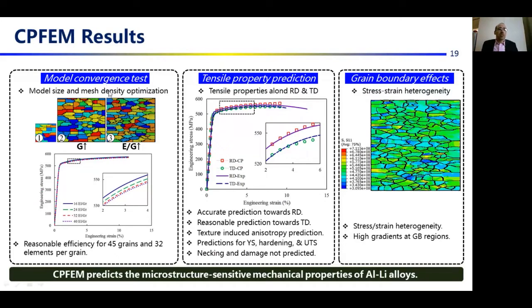For the CPFEM results, firstly, the model mesh convergence ensures the accuracy and efficiency of the CPFEM models by adjusting the grain numbers and elements per grain numbers. Tensile property prediction shows that CPFEM can predict the microstructure-sensitive anisotropic tensile properties consistent with the experiment. And the model can also predict the stress-strain heterogeneity and the high gradient at the grain boundary.